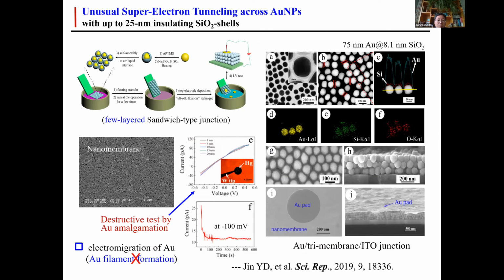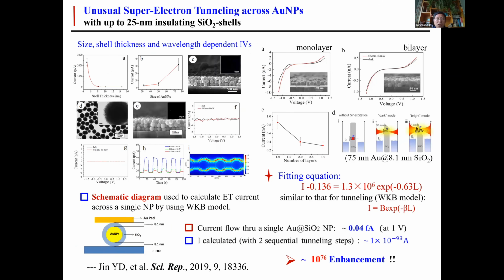We then prepared the nanomembrane with increasing shell thickness of silica and built it into a layered sandwich-type junction. The device withstood a harsh destructive test by gold amalgamation, so the contact artifact in our system can be ruled out. Very interestingly, we show a nonlinear IV response of our device. We revealed unusual super electron tunneling regimes with up to 25 nanometer insulating silica shells.